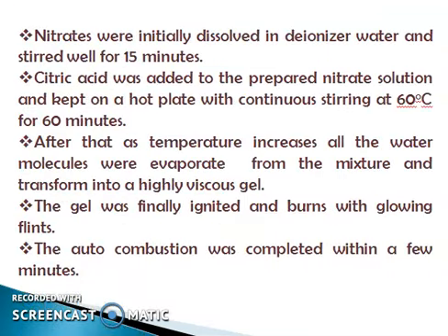We can clearly observe the process of this Sol-Gel method from this. Here we consider the elements like nitrates, which are weighed in the desired stoichiometry, and this composition is dissolved in a minimum amount of distilled deionized water according to molecular weight.